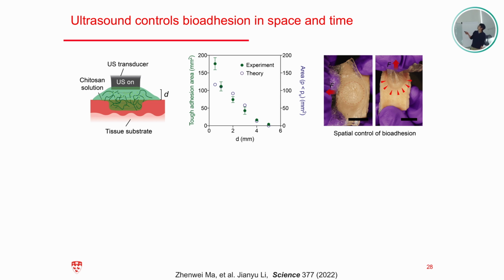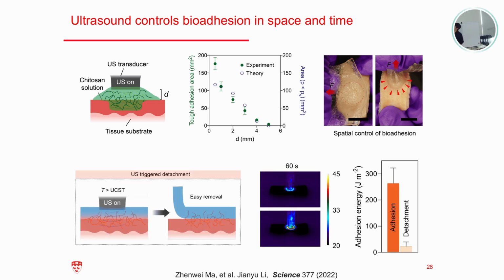That's just a demonstration showing that with the application of ultrasound, we form adhesion only in that specific area. In the other area, even though you expose it to this adhesive solution, it doesn't form adhesion. And furthermore, you may know that ultrasound, in addition to cavitation, has other effects, right? The most notable effect of ultrasound would be the heating. You can feel the heat. In this case, we can further leverage this additional benefit of ultrasound to enable on-demand detachment.